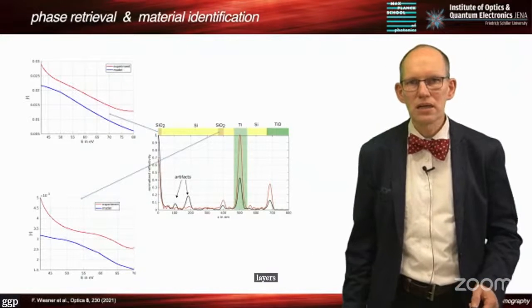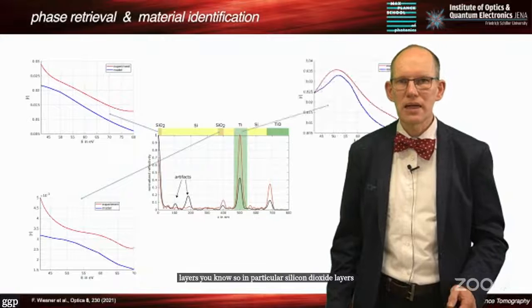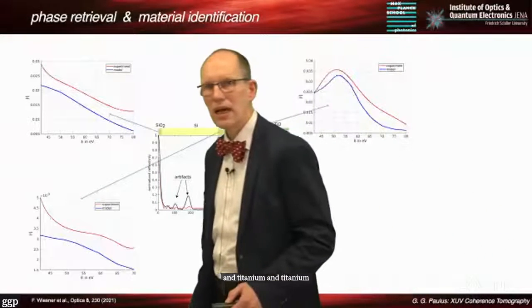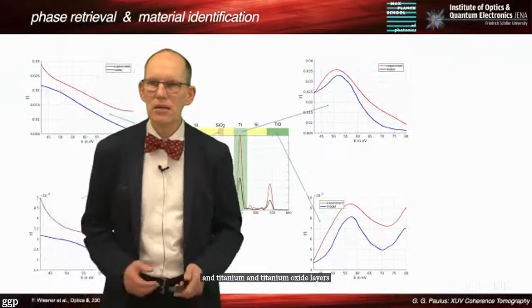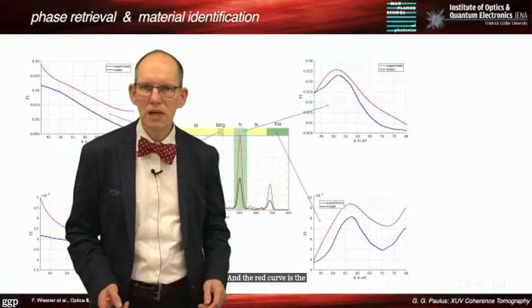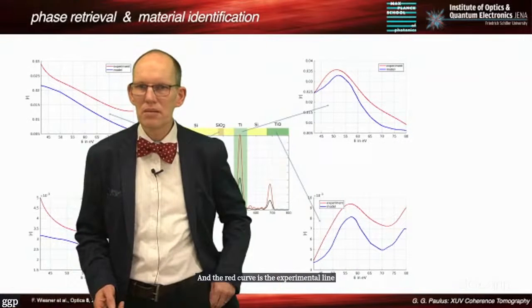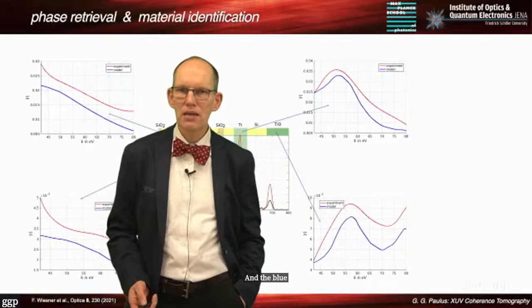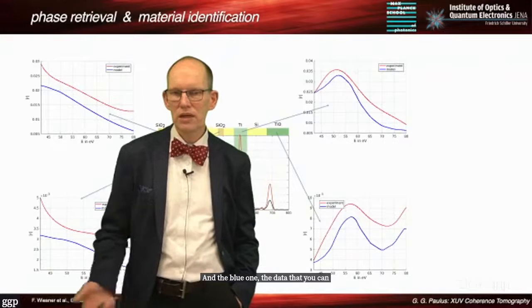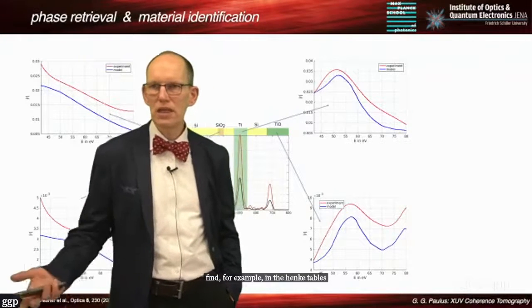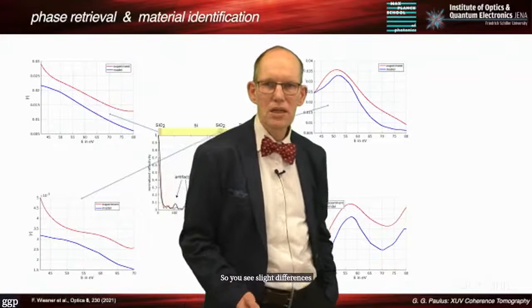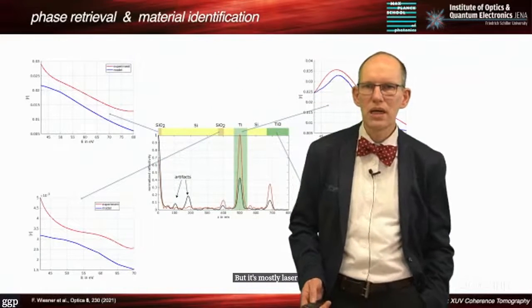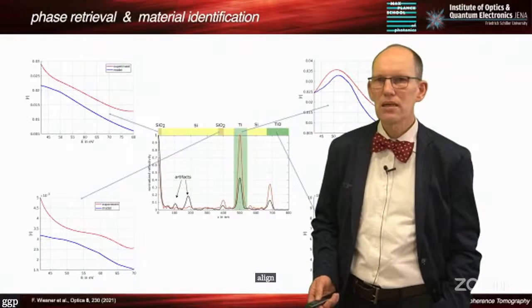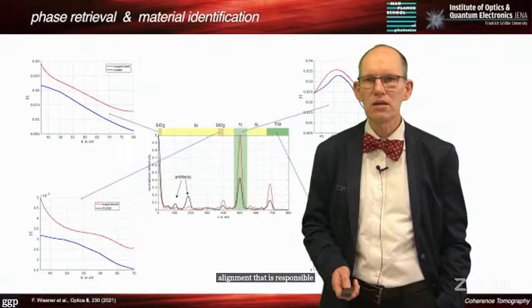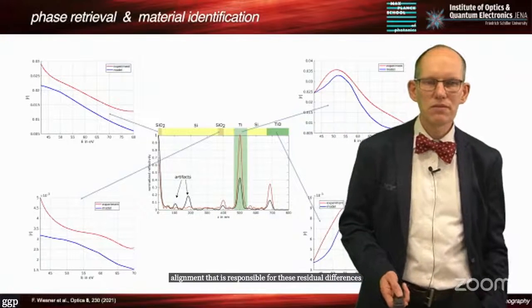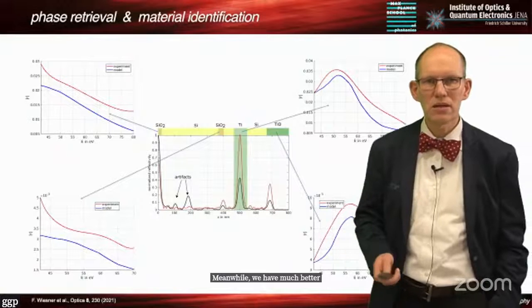In particular silicon dioxide layers and titanium and titanium oxide layers, right? The red curve is the experimental line, and the blue one is the data that you can find, for example, in the Henke tables. So you see slight differences. We think that it's mostly laser fluctuations and spectrometer alignment that is responsible for these residual differences. Meanwhile, we have much better examples. I'll show this later.